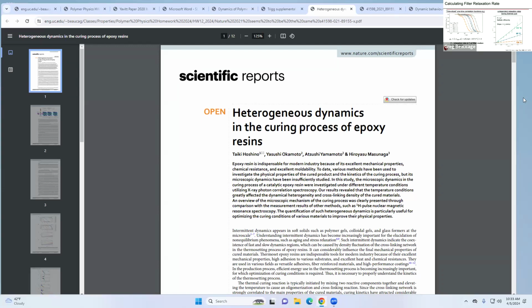And then those slices come out into these nice exponential decays, these now one-time correlation functions that are describing the dynamic process and dynamic behavior, right? So we like to call this quasi-equilibrium dynamics. It's not necessarily at equilibrium, but we do the integration in the assumption that things are not changing at that one time that we're looking at from the process, okay? So that was really cool because the colors show, this is exactly what we were seeing on the plot, right? As we increase time, that characteristic relaxation time that this dynamic process is decaying at increases. So basically the particles are moving slower and slower and slower as we go through that curing process, right?